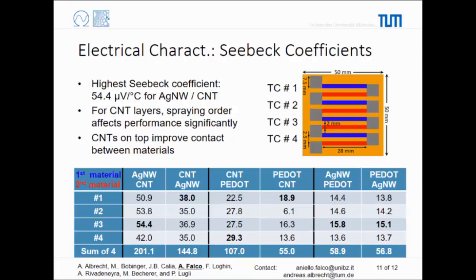Our best thought is that by depositing the CNTs after the silver nanowires, we're somehow having a better interface, and that could be due to the fact that we need to put CNTs in water in order to remove the dispersant, and that also helps to clean up the silver nanowires from the PVP.